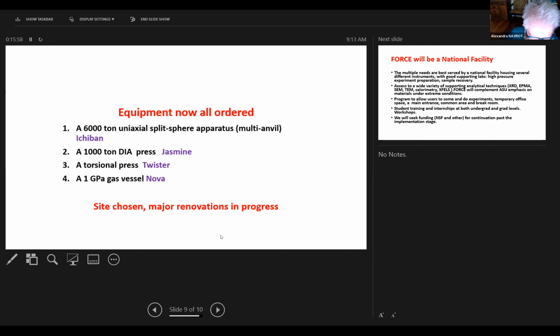We're going to get a torsional press, which we're calling Twister, basically, which will enable the study up to a few tens of GPa at temperatures up to a few hundred degrees C, with the hope of extending the temperature range to really look at the effect of twisting, the effect of torsion on high pressure materials, on their physical properties, phase transformations.